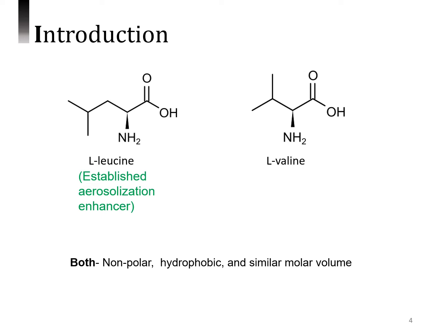Next, looking at techniques to improve aerosolization. Use of excipients is a common effective technique. Among various excipients, leucine, an amino acid, is a proven aerosolization enhancer, and the mechanism of its effectiveness has been ascribed mainly to its ability to introduce surface asperities. These asperities can improve the deagglomeration process by decreasing cohesive van der Waals force by increasing the effective distance between the particles. In addition, they can improve the aerodynamic behavior.